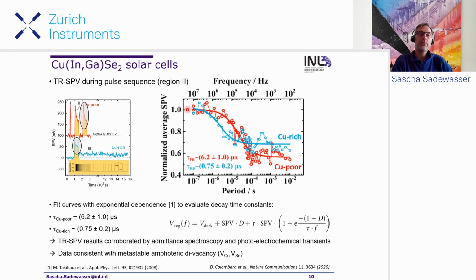However, as we saw already before, since this doesn't decay to zero, this also stays here at a higher ratio, and this indicates the metastable defects. And what we also observe is that the copper poor material, which is the better optoelectronic material, decays slower, whereas the copper rich material is about 10 times faster in this decay time here. And here we used a simple exponential fit.